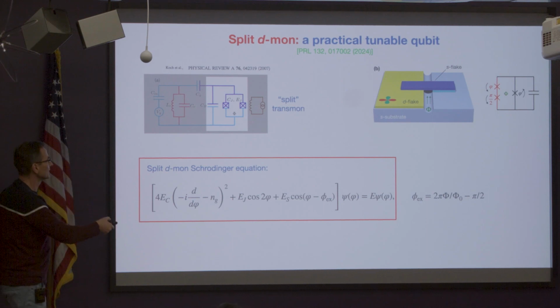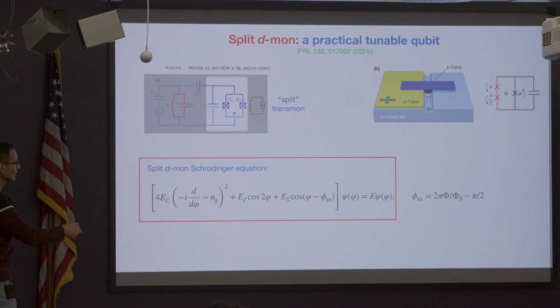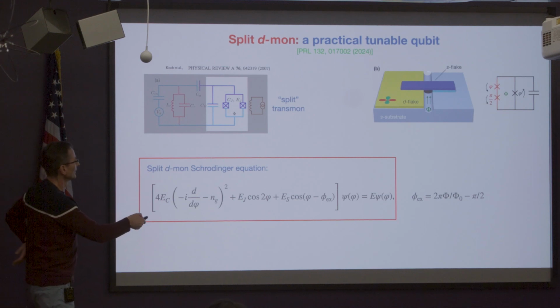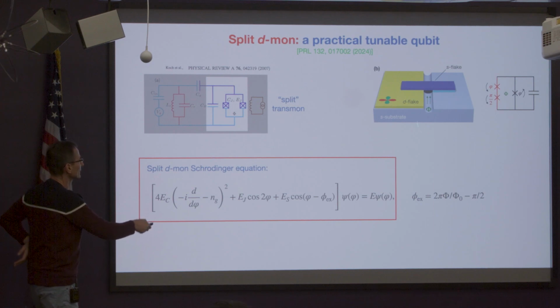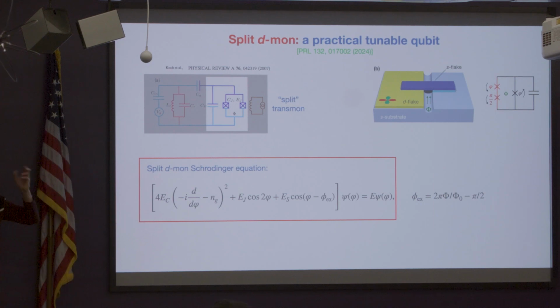Instead of that very simple design with just one D-wave flake on top of an S-wave substrate, this is a sort of more elaborate proposal where we have a D-wave flake on an S-wave substrate, and there's another superconductor on top, such that we have precisely these multiple Josephson junctions. In this case, we have 3. Two of them are these red junctions between D and S, and one of them is just an SS Josephson junction. And the reason for this construction is such that we can put some magnetic flux through that loop and control the